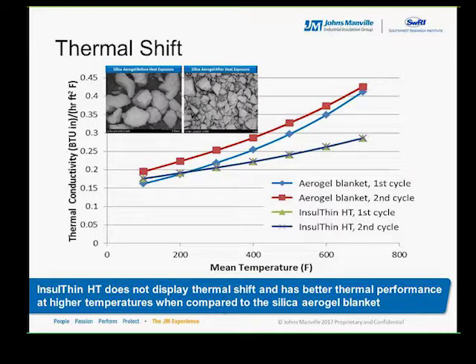To address some of the thermal degradation differences that I just presented between the two different blanket installations, what we did is we reviewed the thermal conductivity data produced from a third party using ASTM C335, which uses a round geometry as opposed to flat. It's important to note that the round geometry thermal conductivity data is much more representative for pipes. This is what we used here, using the actual process compared to the flat thermal conductivity data.